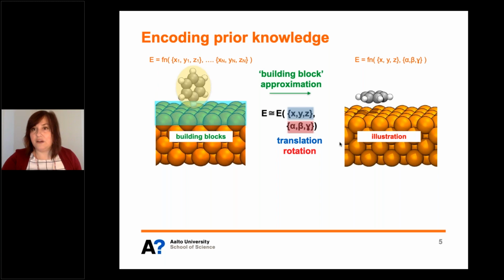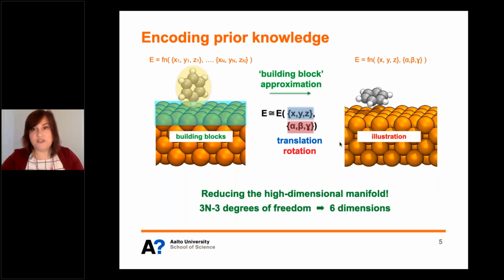So here, if you want to really look at how the orientation works, this is an example. The translation is described by this XYZ translation of the center of the molecule, and the orientation, as shown in this animation, by rotations with respect to the X, Y, and Z axes. And what this does is it takes the energy from a very large dimensional problem of every single position of every single atom in the system to a function of effectively 6 variables, the position and the orientation of these molecules. This dramatically reduces the search space that we have to handle, and effectively also allows us to not worry about the chemical search space, but only about the configurational search space.